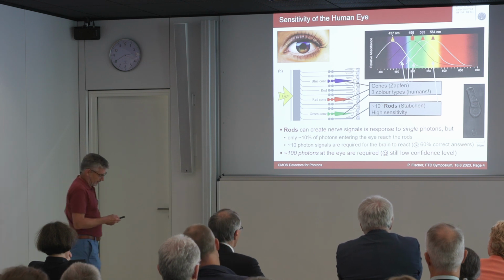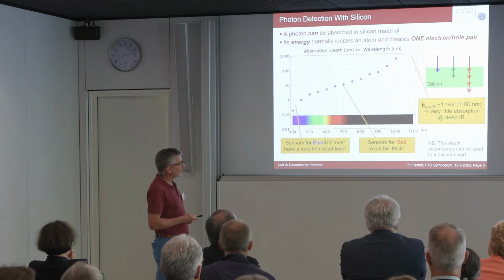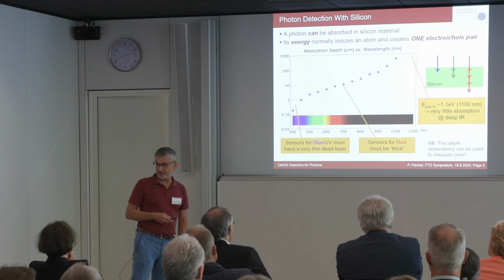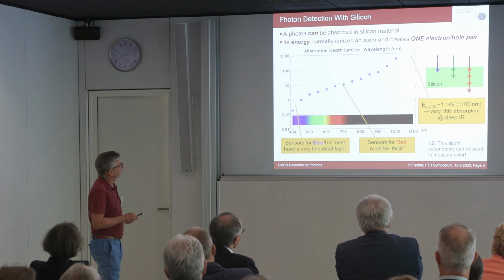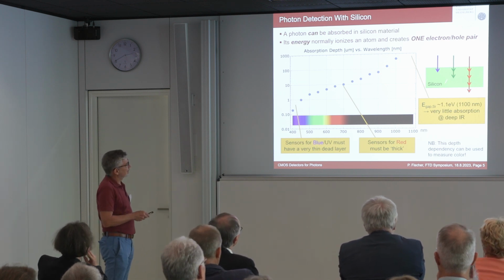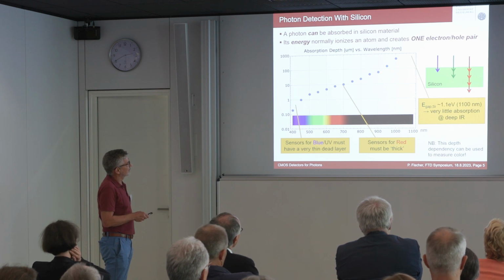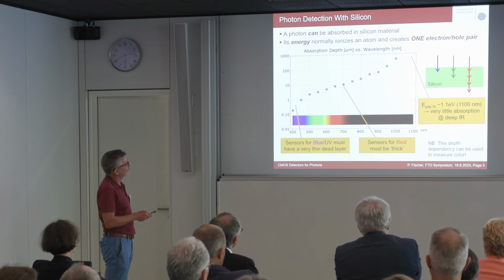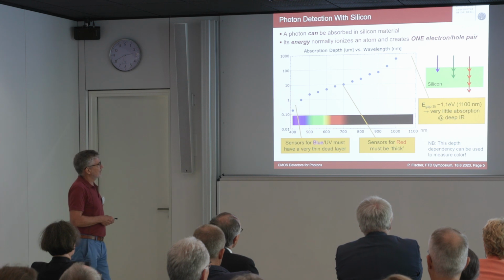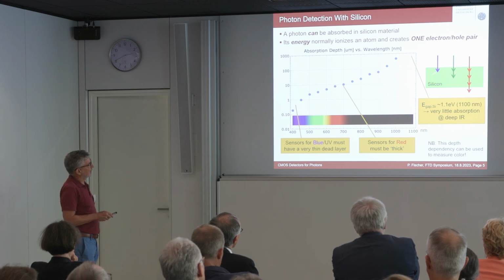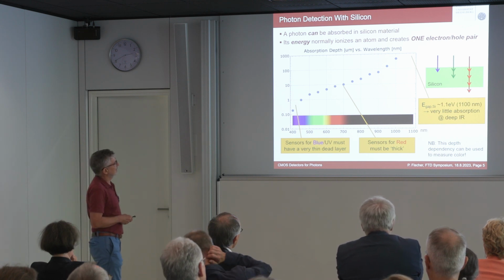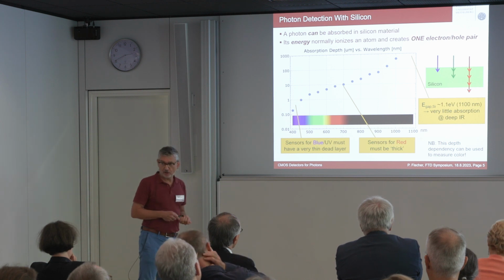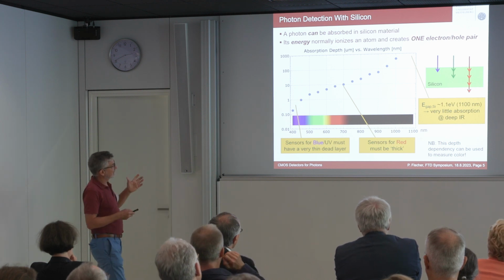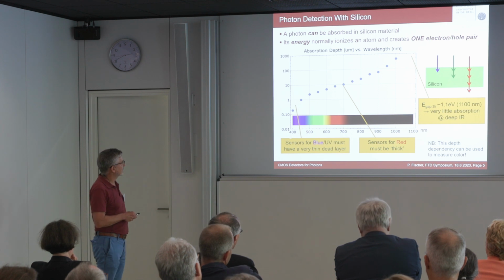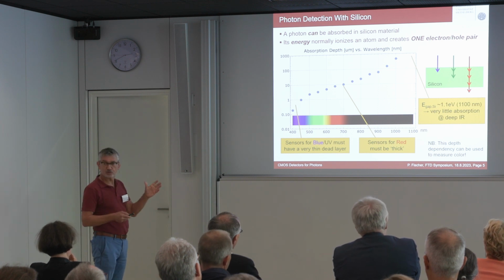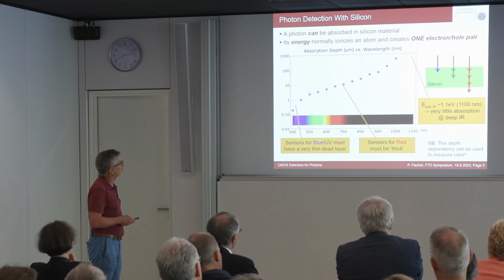Okay, now, we want to detect photons with silicon. We are still in the silicon world. So at some point, we have to absorb the photons with the silicon. If we have a piece of silicon and photons go in, first observation is that the interaction of the photons with the silicon depends on the energy of the photons. And we are really lucky that the energy of visible photons is just in a good range for silicon. Not optimal, but a good range.